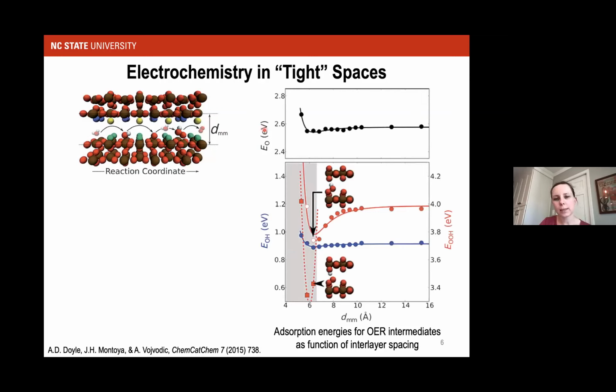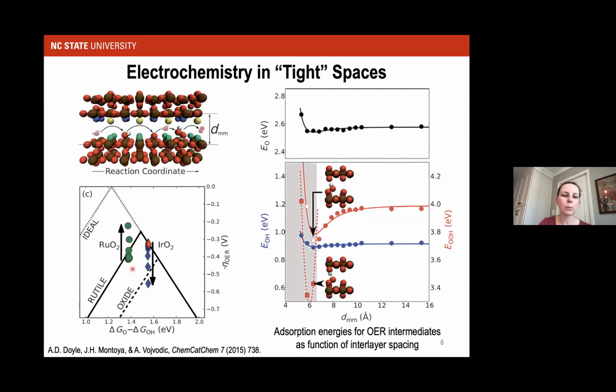And what they find is that the adsorption energies of the intermediates, and those intermediates are oxygen, singlet oxygen, hydroxide, and oxyhydroxide, that in the case of the oxyhydroxide, you actually have this very strong dependence on the interlayer spacing, whereas the other intermediates did not. And this would still give you an opportunity to tune the overpotential or decrease the overpotential of the ruthenium oxide because you were able to decouple the hydroxide and oxyhydroxide and the oxide binding strengths from each other due to this dependence on the interlayer spacing. So in a way to basically overcome what are called scaling relationships.